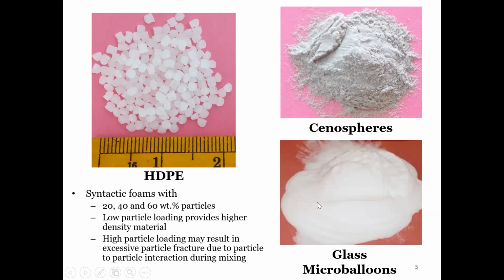So this falls under the natural system, and there is an artificial system also available known as hollow glass micro balloons, which are also available commercially, wherein the particle size is typically around 50 microns. Here, the particle size for cenospheres is around 75 to 120 microns. So these particles drive.